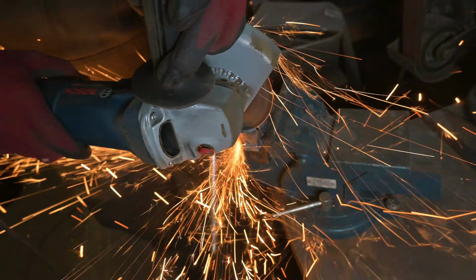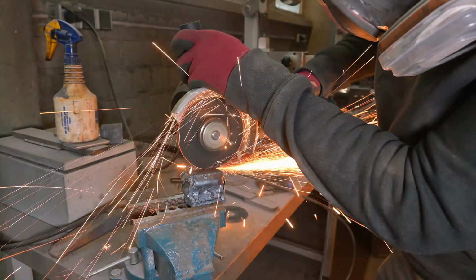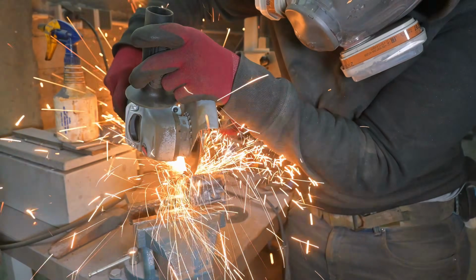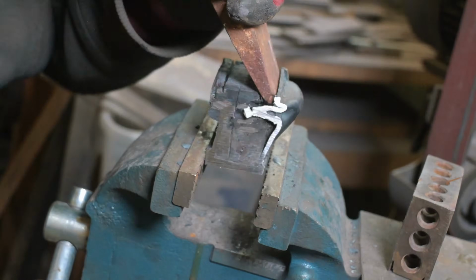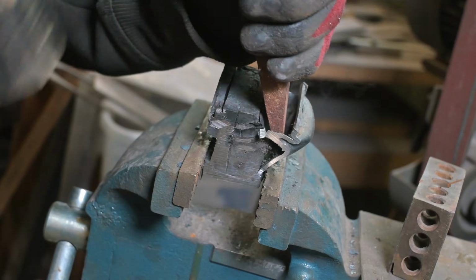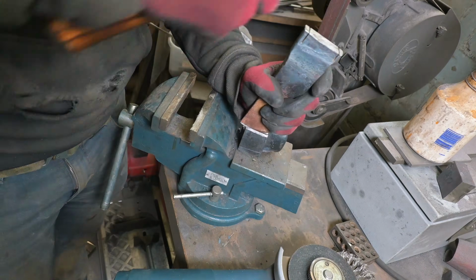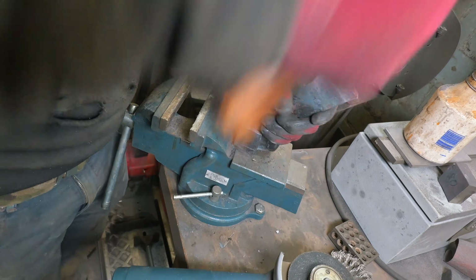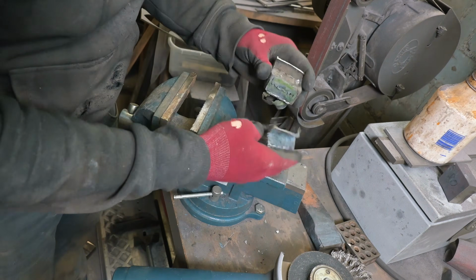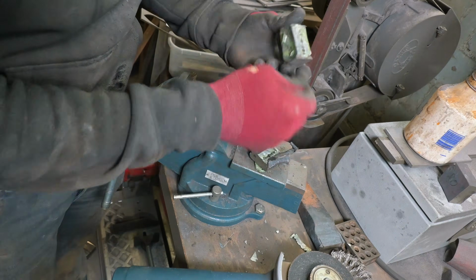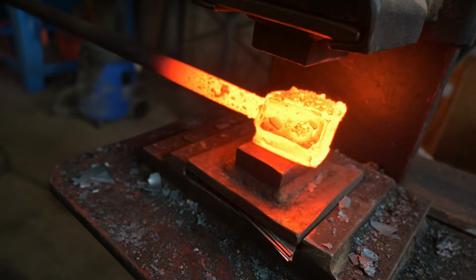Splitting the canister from the material that was inside worked pretty well. With the angle grinder and the steel wedge I could split them really easily. What I then noticed was kind of worrying me: the bottom layers weren't bonding really well. I should have probably used a different die on my press to forge weld them. I have to build this die first for the next project.